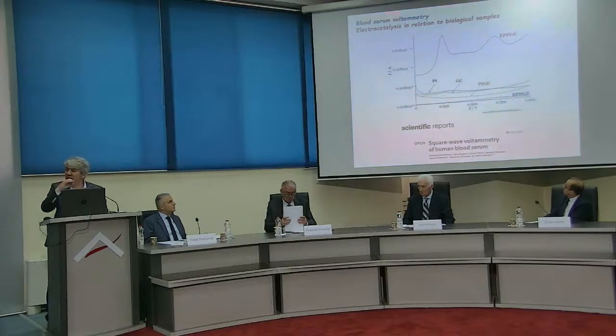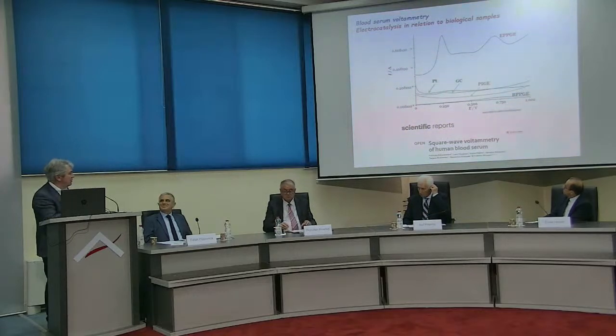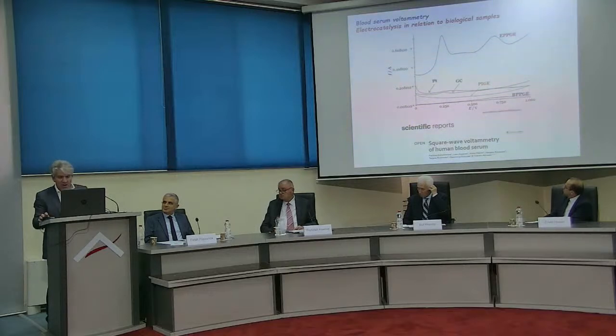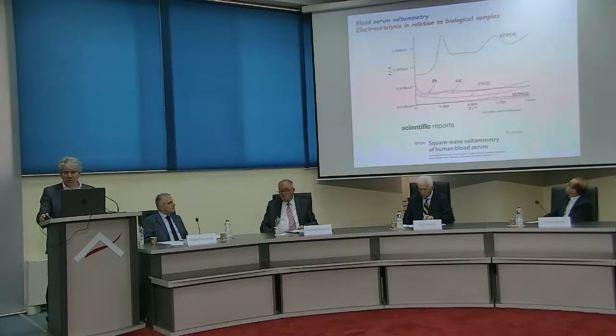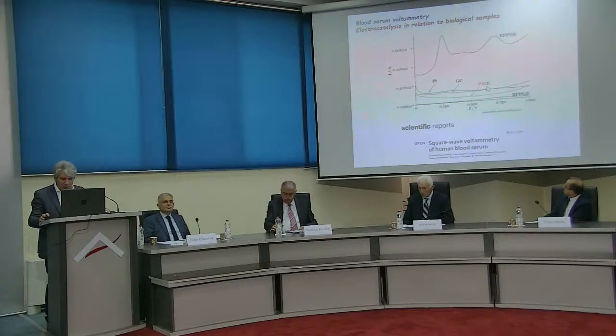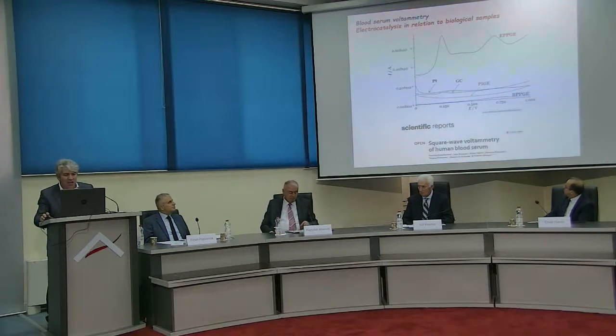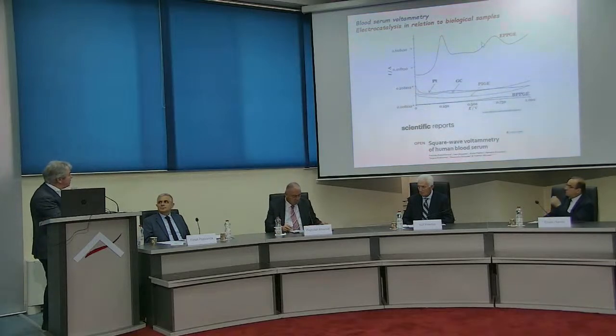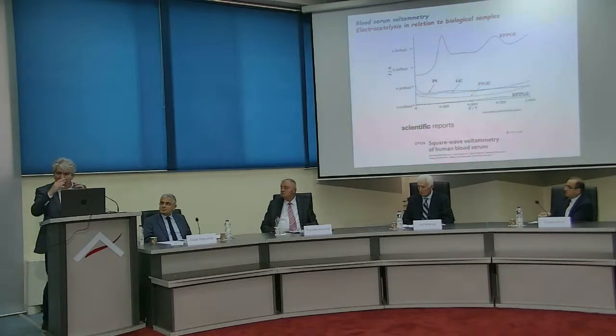We tested several electrodes, you see, and this is the classical example of electrocatalysis. We take a basal plane pyrolytic graphite electrode, no response. Paraffin impregnated graphite electrode, no response. Glassy carbon electrode, something very weak, not distinguishable. Platinum electrode, almost nothing. If we simply take an edge-plane pyrolytic graphite electrode, even a commercially available edge-plane monocrystal oriented pyrolytic graphite, then we see such a beautiful and strong response.